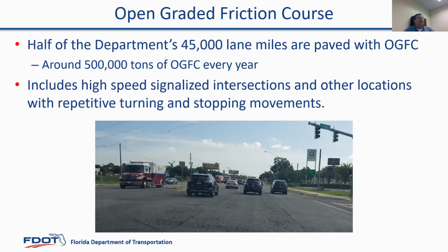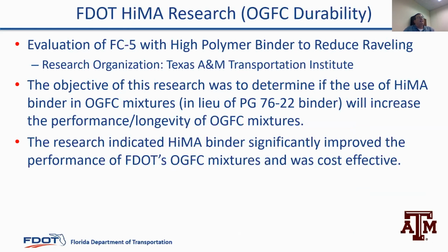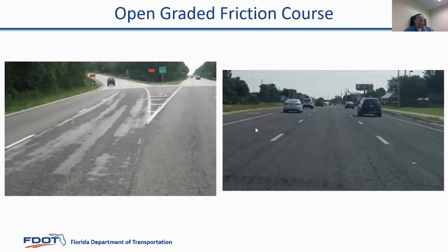And so the research we've done shows that we can get better raveling resistance. In this case, that was research done by TTI. There's the title of the research project if you want to Google it and get more information. But the objective of the research was basically to determine if the high polymer binder in the OGFC in lieu of the polymer modified 76-22 binder would increase the performance and longevity of our open graded mixes. And so the research did conclude that yes, it does significantly improve the performance to the point where it was more than cost effective to have the increased cost of the HiMA binder in the mix. So some places where we would look to use it is where we see raveling. We don't use it in all our open graded friction course, but places that have a history of raveling or where raveling might be anticipated.